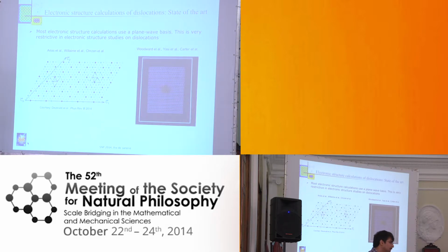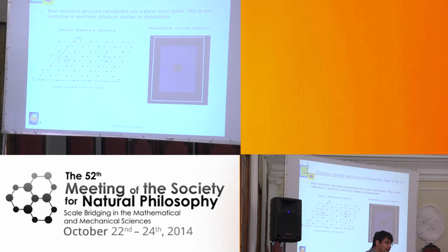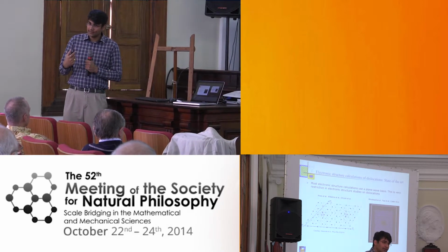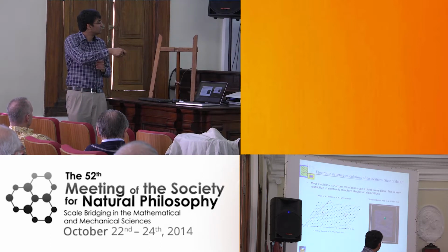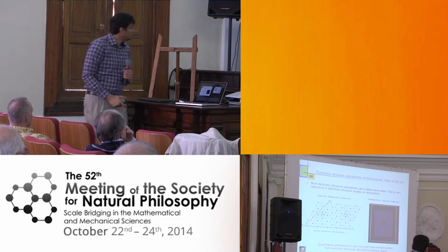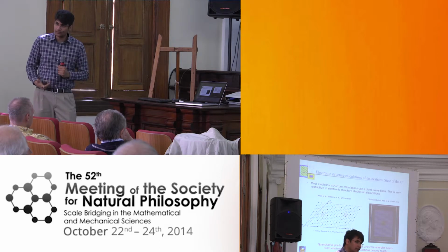The other way people did these calculations is that they considered an isolated dislocation, but since they have to use plane wave basis, the geometry of this domain is not compatible, so they introduced vacuum around here. In this case, you can get the core structure correctly, but you cannot say anything about the core energy of a dislocation, because the energetics are polluted by the surface energy that you have from the vacuum out here. So previous DFT studies were able to say something about the core structure, but they were never able to quantify the real core size of a dislocation and the core energy of a dislocation. These were things that were not able to be answered before.